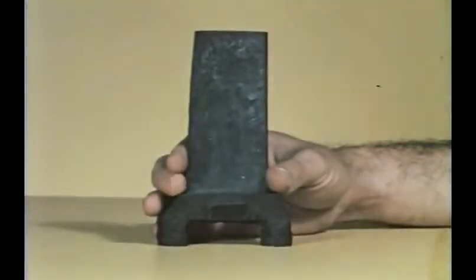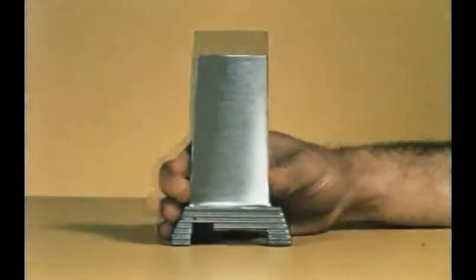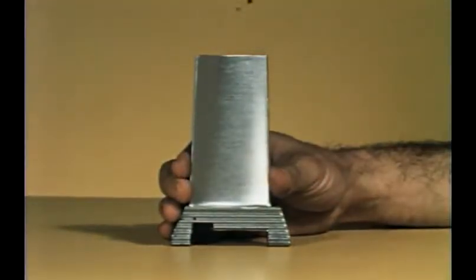The rough casting is cleaned in an air-water abrasive blast. A suitable base configuration is then ground, and the blade is ready for testing in a research facility. The process you have just seen illustrates a principle that has been effective in producing long, thin-cored holes in castings. This process may be useful in fabricating turbine blades to be used at very high turbine inlet temperatures.